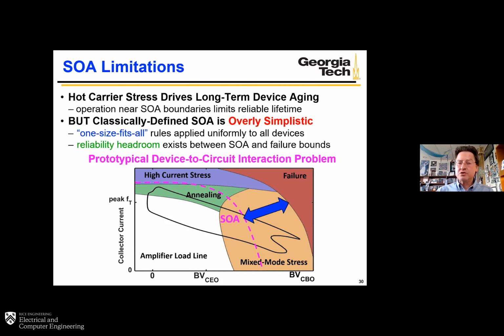But it's important to appreciate this sort of single curve SOA is a ridiculously oversimplistic problem. What industry has classically done is to take a one-size-fits-all approach to apply to all devices in all situations, and that clearly is not the case. The other thing to say is, if you look at the blue arrow, there's a substantial window of opportunity. I call it reliability headroom between the actual SOA boundary and where the device gives up its life and fails. You could say, well, it's nice to have a boundary there, but effectively what you're doing by staying way too conservative on the SOA is to throw away device performance.